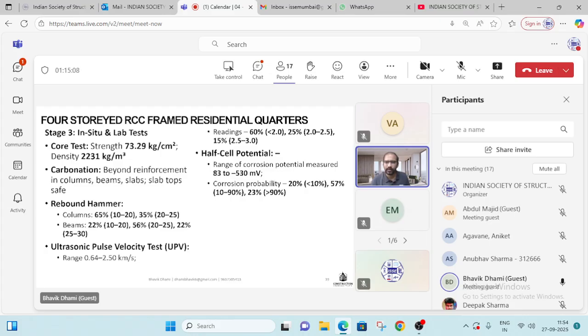In half cell potential, we can see the corrosion probability. For 20%, the probability of corrosion was low, but 57% indicated uncertainty, and 23% indicated a 90% probability of corrosion through the half cell potential. Doing some chemical analysis, we were able to find that there was sulfate in the concrete structure.